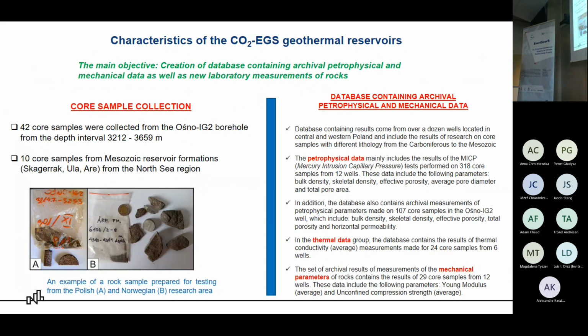For these locations, first of all, we collected data. We started from collecting archival data to know some petrophysical and mechanical parameters. After that, we collected a total of 52 core samples. 42 core samples were collected from the Ośno IG2 borehole. It's a borehole located in the Gorzów block. This is our first location. From an interval of about 3,200 to 3,600 meters. 10 core samples were collected from Mesozoic reservoir formations, from the Skagerrak, Ula and Are offshore formations.